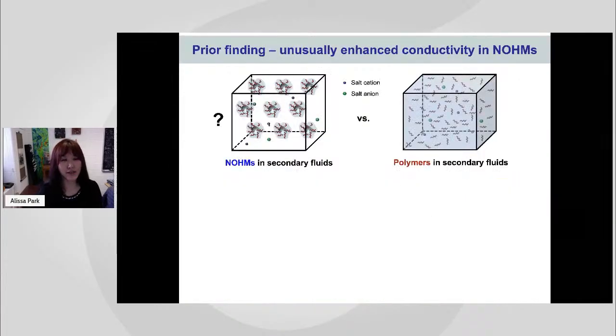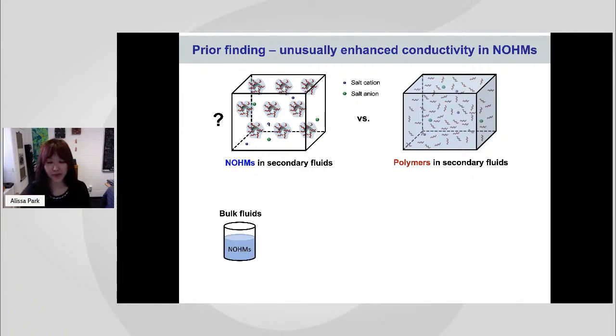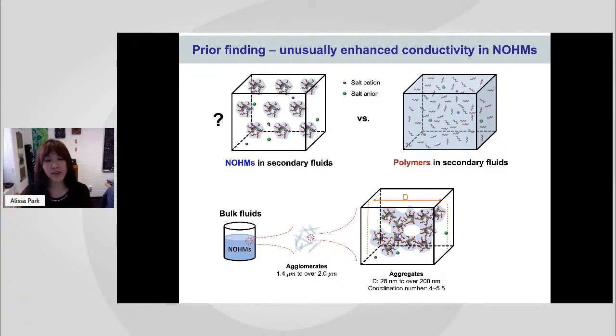So now looking at this, we have this vision of our material. Structure of this material is, if you look at the bulk fluid, it's still transparent, a very well mixed system, which we imagined. But if you really zoom in, you'll see agglomerates at less than 2 micron size. And then if you really zoom in, you see aggregates at tens to hundreds of nanometer scale. And because of that, there's a lot more interaction between NOHMs, each fluid unit. And because of this hierarchical structure, the transport behaviors were very different. So maybe there's some channeling, possibly through different pockets, and there'll be multiple ways of transporting different ionic species or even CO2 throughout this electrolyte.